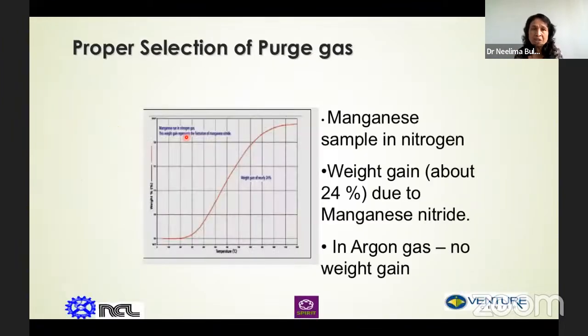I was talking about the purge gas. Now I'll show you this sample. This is a manganese sample, and suppose we run the manganese sample in nitrogen. Generally, people come and tell me that they want to do their TGA in an inert atmosphere, and the inert atmosphere is nitrogen. But if you run your manganese sample in nitrogen, the manganese reacts with nitrogen and forms manganese nitride, and then you get a weight gain in your sample. So when you are using a manganese sample, you have to go for argon gas, where there will not be a weight gain. So a priori, you should know your sample a little bit also.